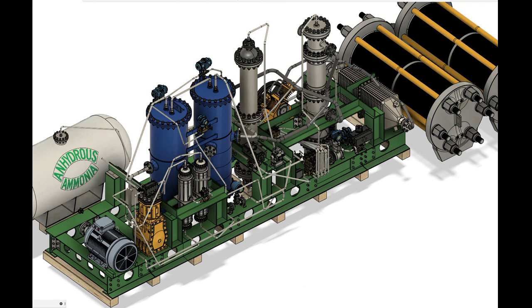If higher pressure drop is tolerated, the designer could bump up the space velocity to 70,000, and bring the yield all the way up to 2.6 kilograms NH3 per kilogram catalyst, while conversion drops by only 2.5% to 16.5%, from 19%. In light of this information, the designer is left with the choice to make a trade-off between catalyst yield, longevity, reactor volume, and compressor size.